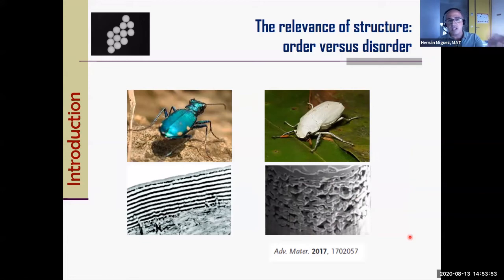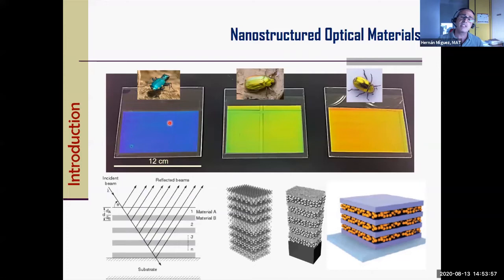So continuing with this and getting closer to the materials that we prepare, you have here another example of how you can control properties with nanostructure. You're looking at three films that have completely different color, obviously, as you can see. But again, here, the chemical composition is the same. They are made of silicon oxide nanoparticles and titanium oxide nanoparticles stuck in a structure very similar to this one that you can see here in this model.